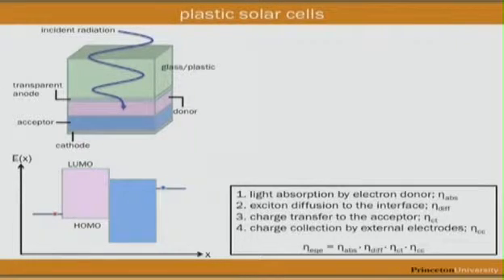So now you begin to appreciate why photovoltaic cells are inherently not very efficient devices. The overall efficiency of one of these cells depends on the efficiency with which light is absorbed. It depends on the efficiency with which excitons diffuse. It depends on the efficiency of charge transfer, and then finally charge collection at the external electrode. When all said and done, the record polymer solar cell has an efficiency of 10%, okay? Compared to silicon, which is now at high 20s, low 30s, all right?